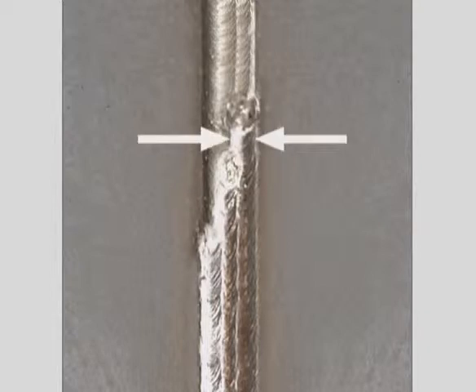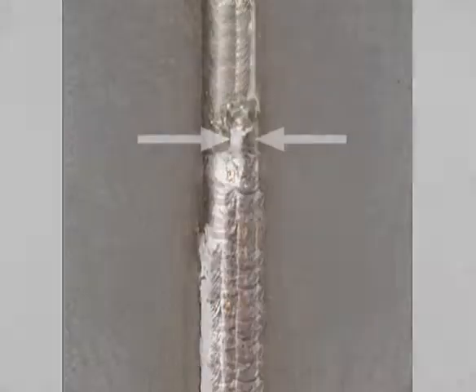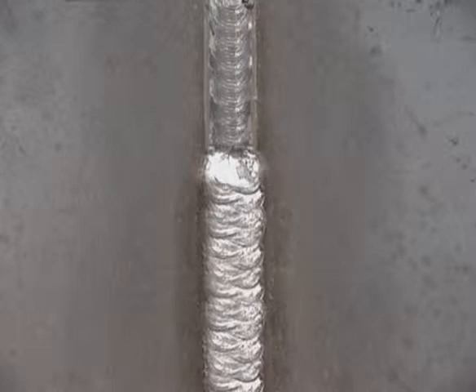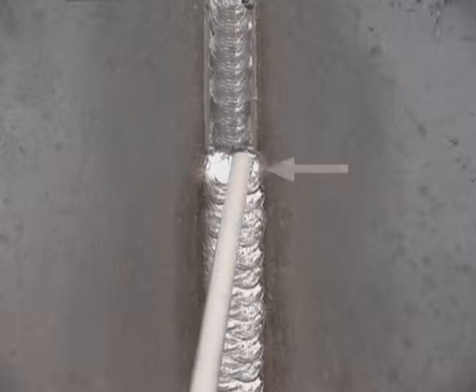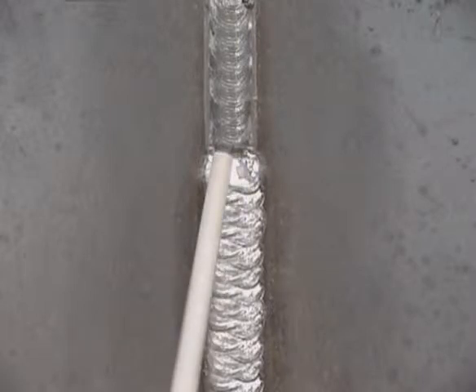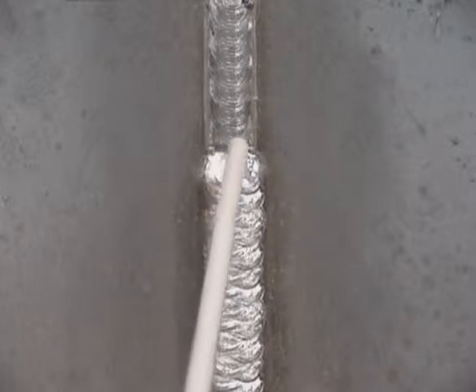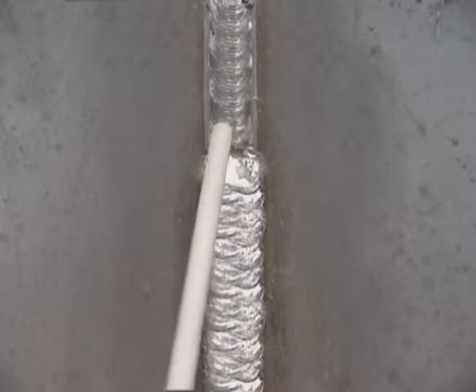If you're not limited to a maximum bead width by a welding procedure, you can try a weave bead. Start on one side, letting the puddle flow out to cover the edge of the bevel. Cross the center relatively quick to the other side and hesitate until the puddle flows out and covers the edge. Move the rod up a little, then cross, hesitate, move up, and cross. The upward progress is going to be slow, heating the base metal up more, so turn the amperage down a little. Use the edge of the bevel as a guide to keep the sides of the weld straight.